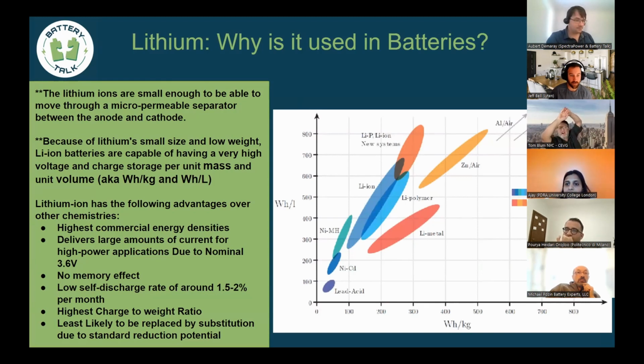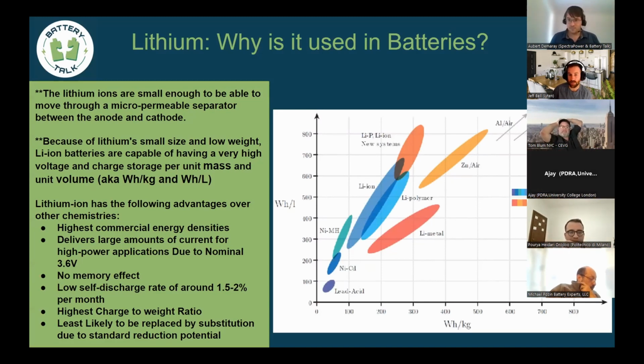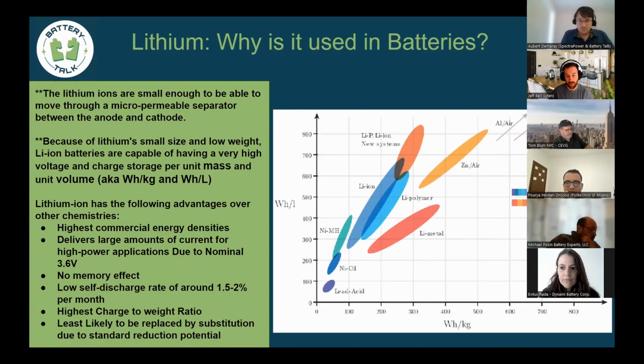So why else? Well, beyond just having the highest commercial energy densities, it's able to deliver a large amount of current to high power applications. And that's usually due to its nominal voltage. If you look at a lot of the other lower voltage chemistries, they actually get penalized. So they can deliver, let's say, an amp of current, but that really only equates to maybe 2 watt hours, whereas with the 3.6 volt nominal voltage window, you get a huge advantage in terms of being able to get that energy out of the system. So the same 1 amp of current that you would get out of a lithium ion battery related to maybe a lead acid would give you 3.6 watt hours versus maybe 1 to 2.